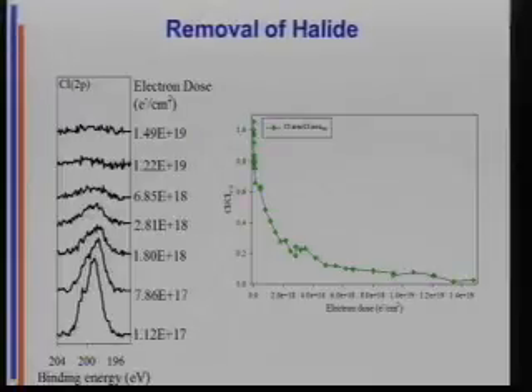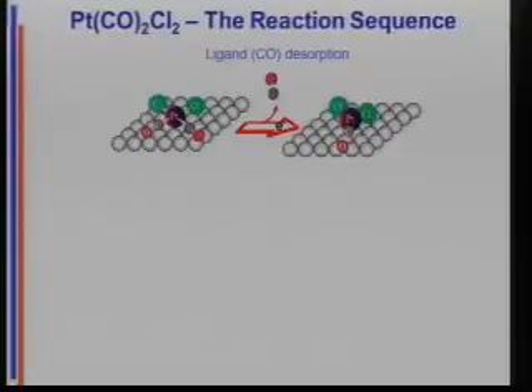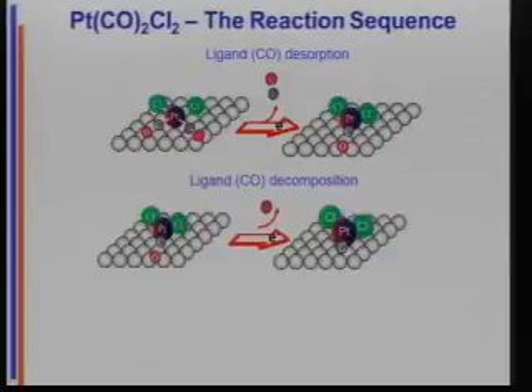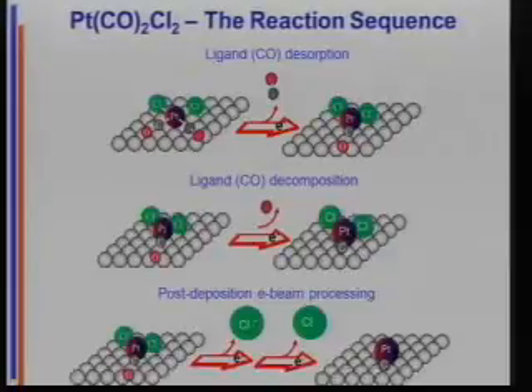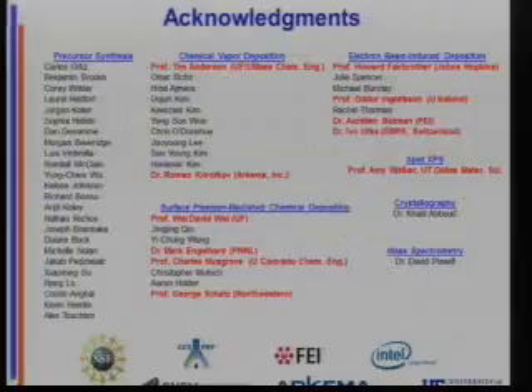So our first shot at precursor design, specifically for EBID, we went from 80% carbon in the industry standard to ours is about 10% carbon. That's not bad for a first shot. Experiments continue. Okay, so there is what happens here. We get rid of carbonyls, we get rid of chlorides, and it's all good. All right, so that's the third story.